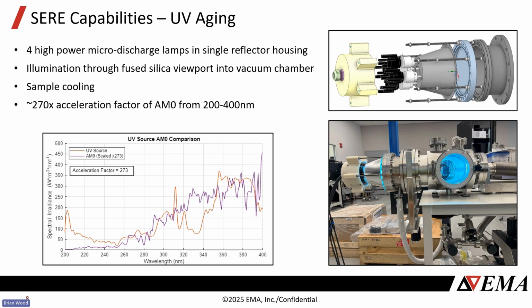But essentially what this means is we're able to age things 270 times faster compared to the AM0 flux that you would see. That 270 can be increased or decreased just by changing the distance of the sample to the sources. This is a good little source we've got that's able to do decent acceleration. If you're trying to age 5 years or something in GEO, we're able to do that relatively quickly.